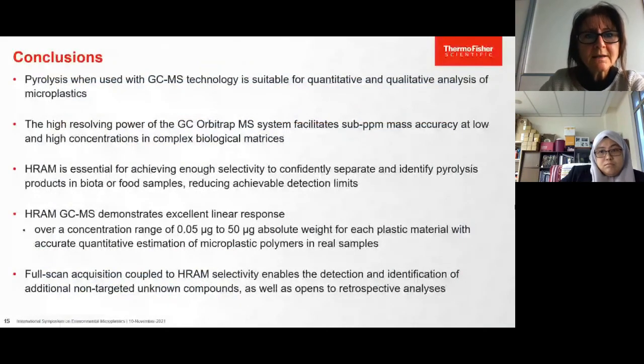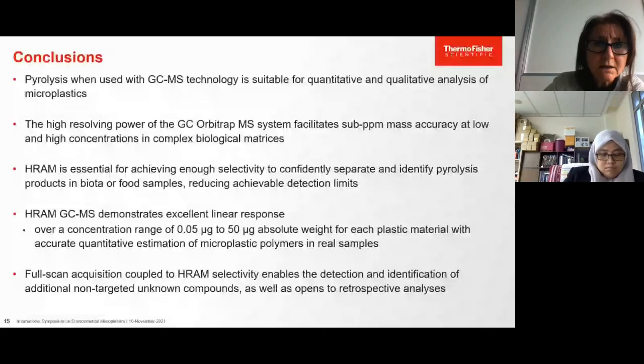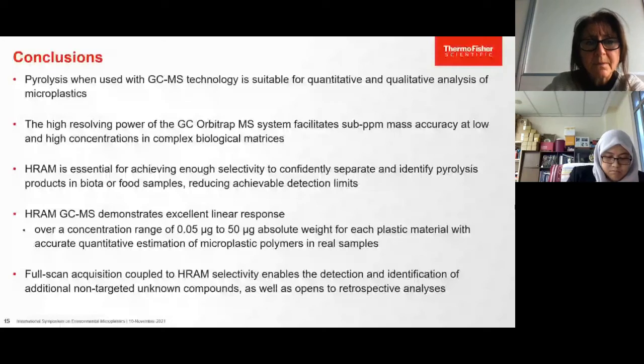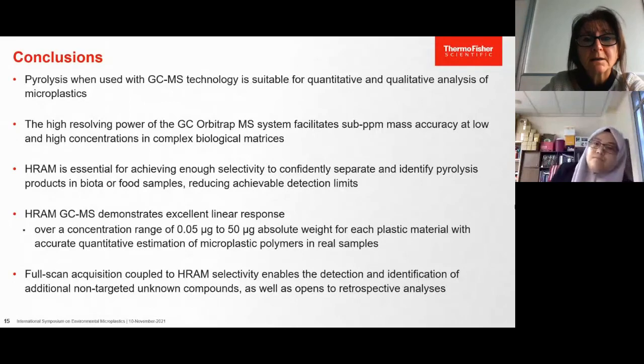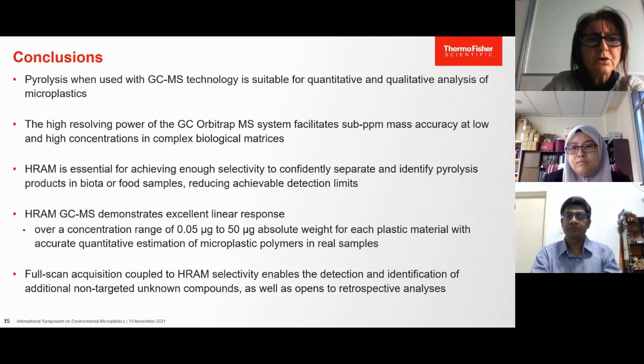So in order to conclude, we can say that sample pyrolysis followed by GCMS analysis is an established available technique for quantitative and qualitative analysis of microplastic in environmental, food and biological samples. Especially for complex matrices, Orbitrap GCMS system in combination with pyrolysis is a very promising analytical technique that opens new possibilities for the analysis of microplastic polymers in biological matrices. This technique has been applied to fish meal samples within a study on the impact of microplastic on the marine life. And the high-resolution accurate mass detection is the key to ensure the required selectivity and sensitivity for confident identification of the pyrolysis products from a complex sample.